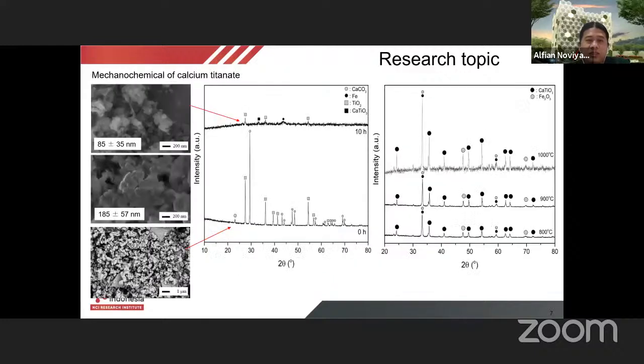Okay, this is the mechanochemical synthesis of calcium titanate. So we will demonstrate how we make calcium titanate from calcium carbonate powder and titanium oxide powder. After 10 hours of milling, we can see the peak of the calcium carbonate has already disappeared, and we observe a new peak of calcium titanate. So without any heating, just milling for 10 hours, we can form new phase calcium titanate using mechanical milling.